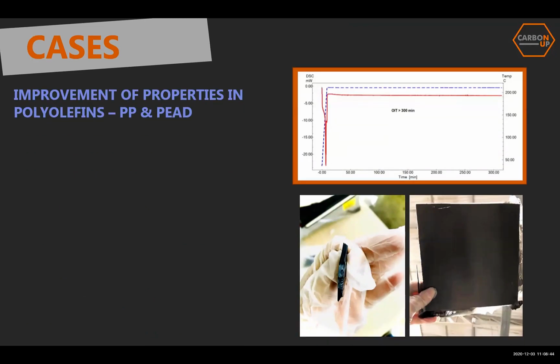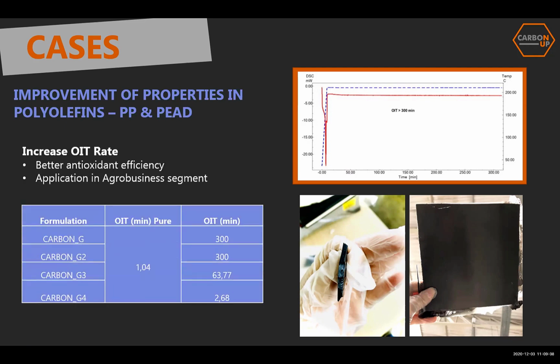Going a little bit fast, this is an improvement that we are very anxious to apply, because we made some formulations with polypropylene and high density polyethylene. I'm sorry for the Portuguese, it's high density polyethylene. And we achieved better properties in terms of antioxidant properties. So what we basically did is we worked with a pure polypropylene, where the OIT time is 1.04 minutes, and you could increase it to 300 minutes. That means that we could have space to work in the agribusiness sector. I mean, for films, for tubes, or for wires and cables. And there is a very good opportunity.